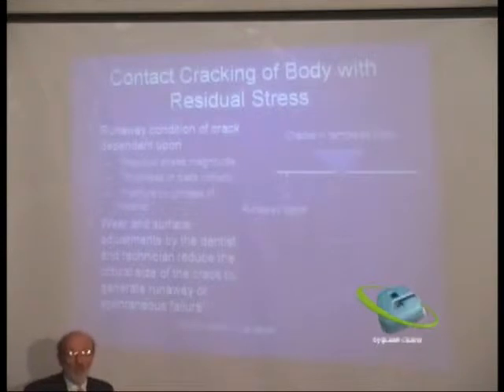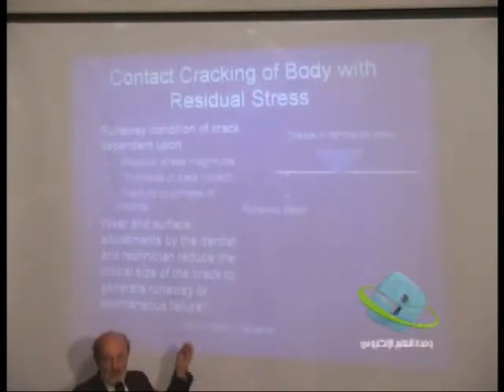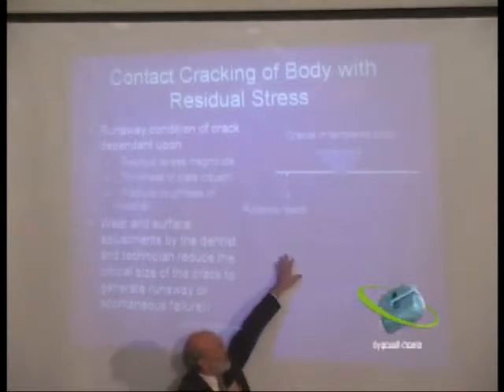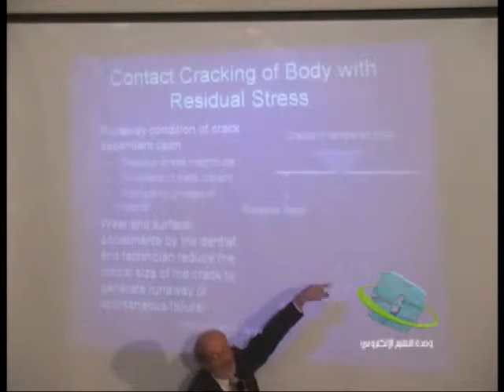And what is really happening? When we do an adjustment or a grinding, initially for a tempered body that has residual stress, it's very hard to initiate and grow those cracks. But subsurface, if there is tension, these cracks get into that and then start to run away and rapidly grow through the system.